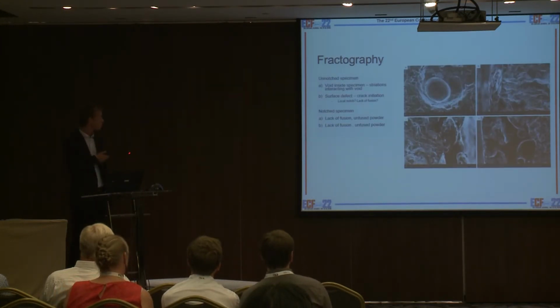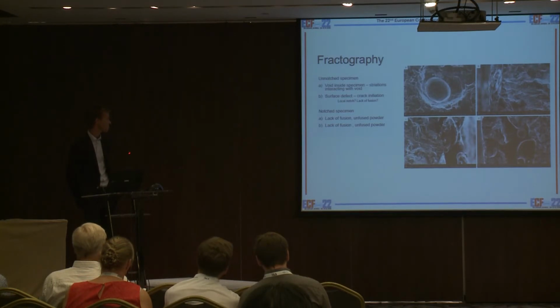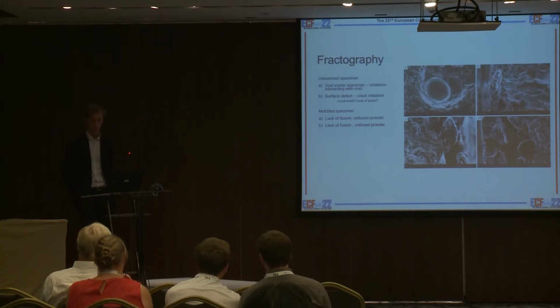So the top two pictures are from the unnotched specimen. We can see, for example, a porosity where the crack is growing through it, and we would see the striations interacting with the porosity. And the right one is the surface defect, which initiate the crack growth. The two lower ones are from the notched specimens, and we can see lack of fusion and the unfused particles, which are of size approximately 30 microns.